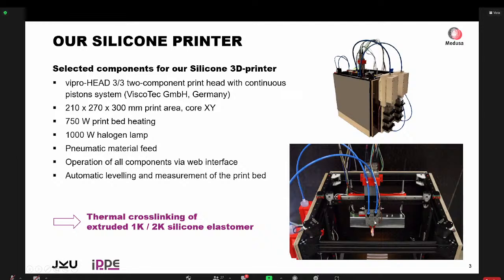Here, then they come into this continuous piston system. It's a conventional dosing system, and only in this part in the front there is the static mixer where they actually come together, and then they're mixing. And at the end, we use the 0.4 millimeter nozzle through which it's extruded. It's still liquid.